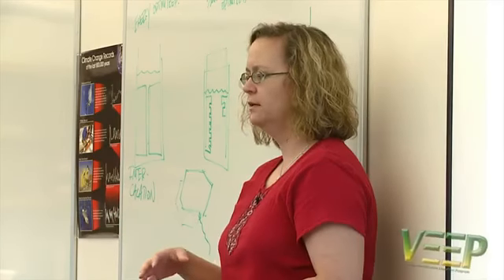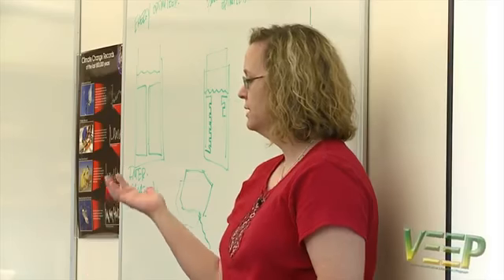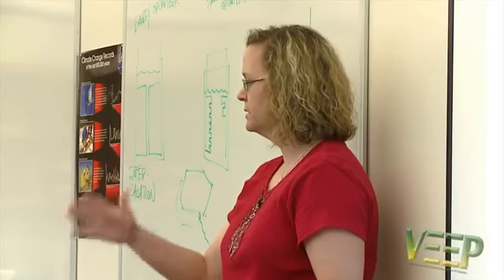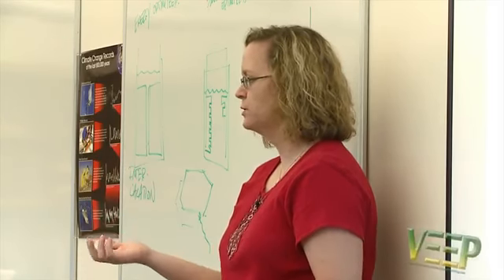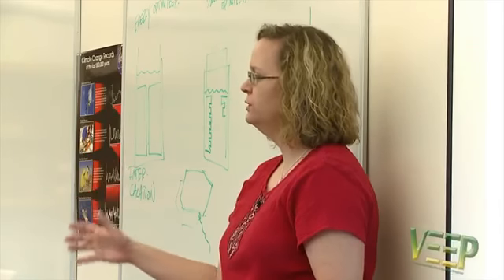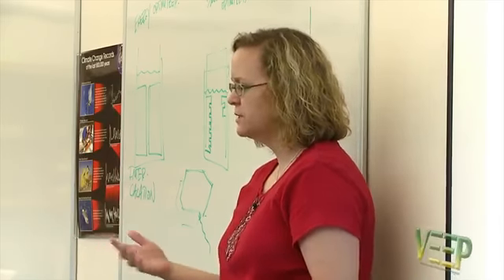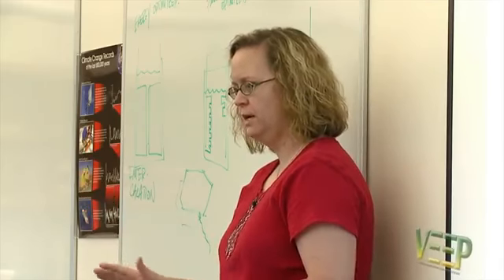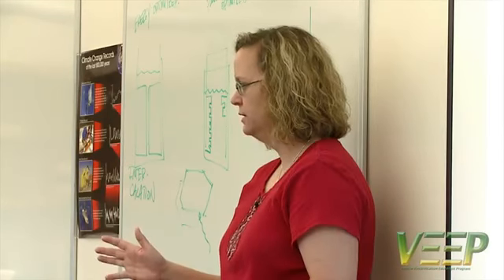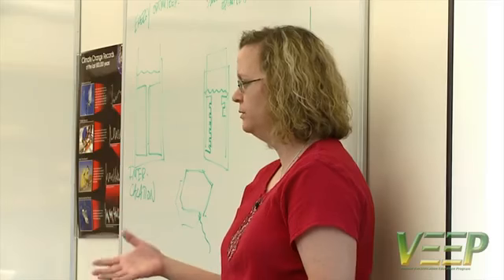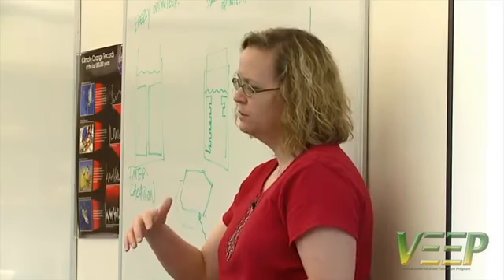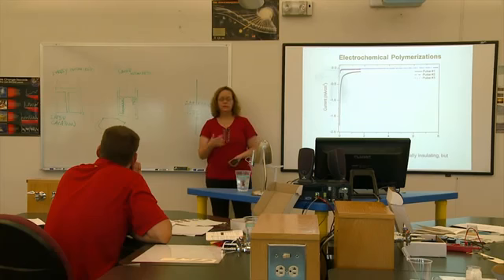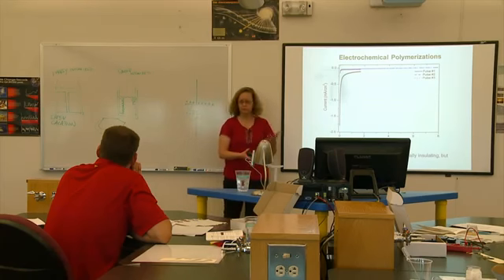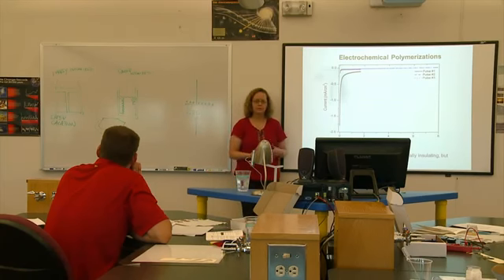And we decided that electroplating was still the best way, because as you make the polymer, it becomes insulating, and so then no more polymer can grow there. So polymer is only going to grow where there are patches, and if you keep cycling, then you will fill everything, and you will end up with no defects anywhere. If there are defects, typically called pinhole defects, then when you add the cathode in, you'll get a short. So the way that we monitor this is we apply a voltage. These are polymer electrolytes that we've developed because there really isn't anything in industry that can be made this way that works the way we need it to.